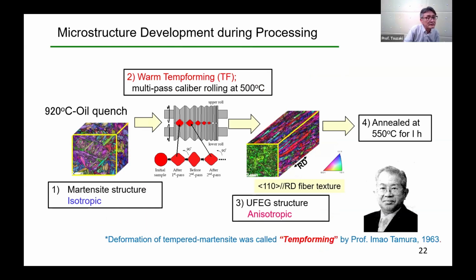Again, this slide shows the microstructure development along with processing. Before processing, martensitic microstructure is isotropic. And the rolling at 500 degrees Celsius creates an ultrafine elongated grain, UFEG, structure. This is anisotropic. We call this process tempforming. And I'd like to point out here that Professor Imao Tamura was the first to call the deformation of tempered martensite tempforming in 1963.